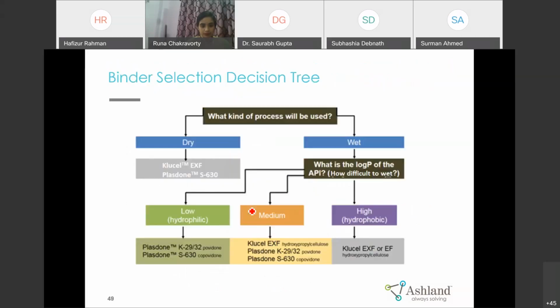So this is our decision tree based on our experience. If you are doing dry granulation, we recommend you to use Klucel EXF. If you cannot use EXF because of some patent issue or compatibility issue, then you can use copovidone. We also have a finer grade of EXF, which is Klucel EXF Ultra. It works much better than EXF because of finer particle size. So that is our first recommendation.